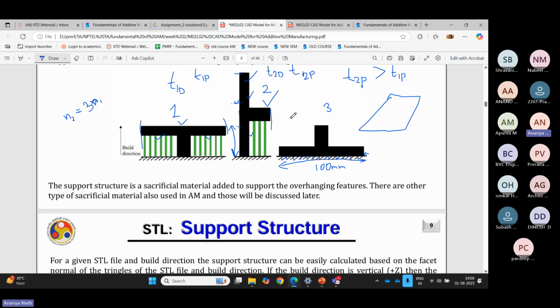But if you are putting support structure beneath, then on the build plate you are not putting that much heat and your layers are not adhered to that big surface. The support structure has another very vital role besides supporting the overhang structure. The support structures are needed to dissipate the heat to the build plate because there will be columns. It's the same as the bridge concept. Rather than making a block, it's better to put the rods in a particular way, like trusses, and then you have the bridge structure. Same here, if you put the support structure, these are small cylinders. It will act as a heat dissipation site for that particular layer to the build plate. So the layers will dissipate the heat faster.